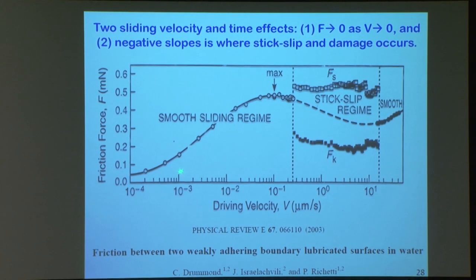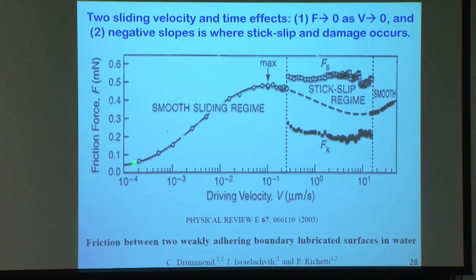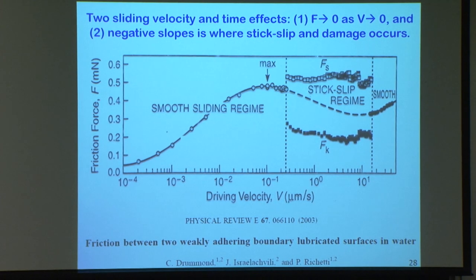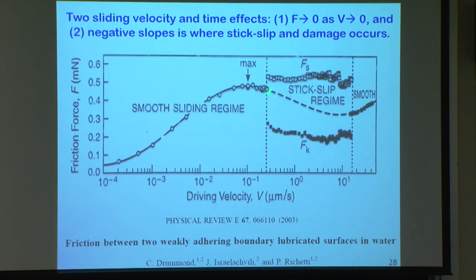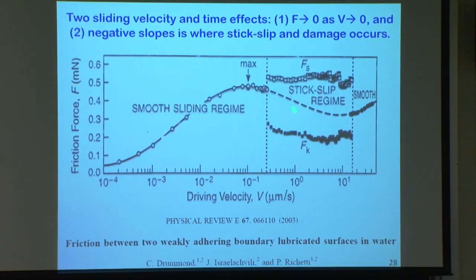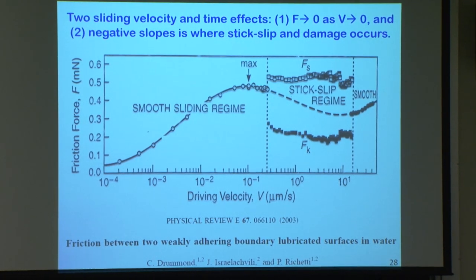The other thing is that this is an experiment that we did some time ago. We go right down to velocities of, this is 1 angstrom a second, and then you can see that over many orders of magnitude, the friction is dependent on the velocity. And very often you see a maximum and then a minimum, a maximum, a minimum. And in the negative slope regime is when you solve the equations of motion, you find you have stick slip. And that's really interesting. Stick slip is a very common phenomenon, and very often people ignore the importance of stick slip friction, just like the stick slip adhesion I showed you when two surfaces separate with polymers, depending if they're elastomers or if they're cross-linked or not. But there can be stick slip and material transfer and complications like that.